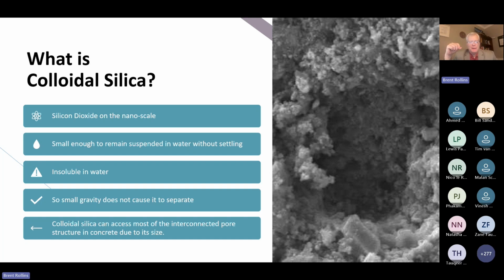That is a tremendous amount of tiny, tiny particles that you can put into concrete. And I'm going to use some examples. That photo of a pore structure that you see is about 20 microns in diameter, or about a third of the average human hair diameter. If we assume that that hole is as deep as it is wide, it will hold about 700,000 average size colloidal silica particles. That small size allows that colloidal silica to get to over 99% of the interconnected pore space in concrete.